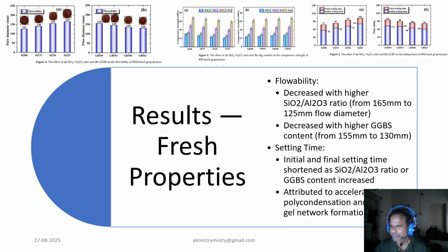The fresh properties showed that increasing the silica-alumina ratio or adding more GGBS reduced flowability. This is because higher silicate concentration increases viscosity and accelerates the polycondensation reaction, forming a dense gel network. Setting times also shorten under these conditions due to faster geopolymerization facilitated by the availability of reactive silicate and calcium ions.